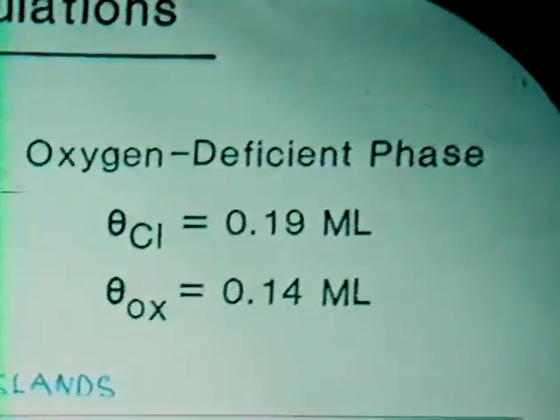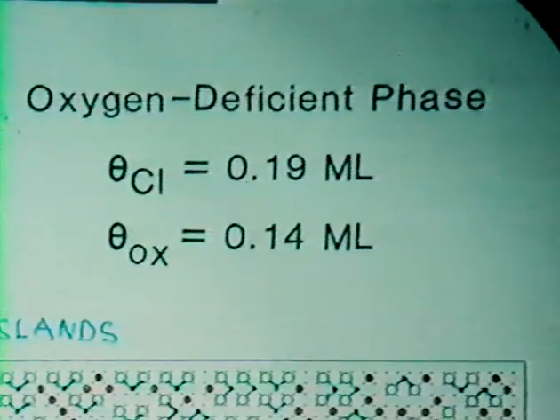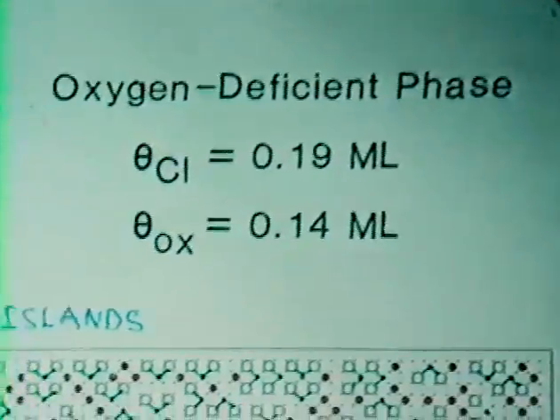And we can put in a lot of dichloromethane to saturation, in fact, which is not that much of a saturation, only 20% of the surface. And then we have dichloromethane fragments, chlorines here and oxygen here.